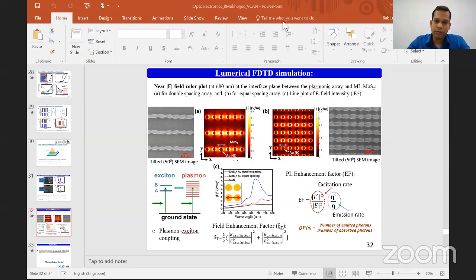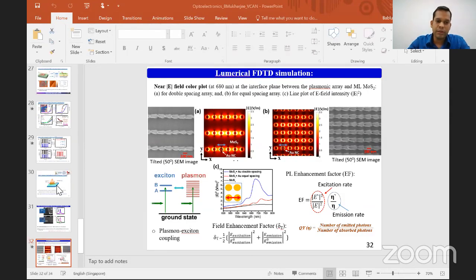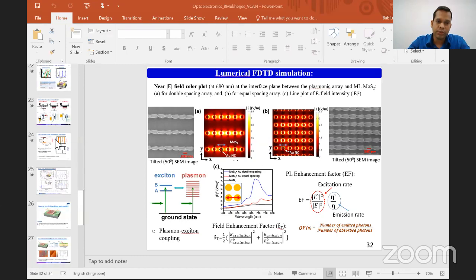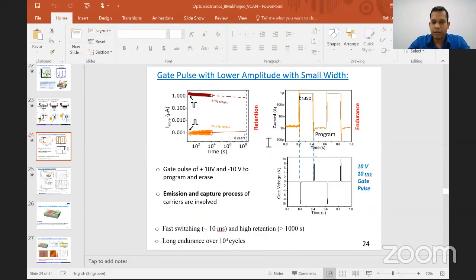Yes, actually, the instrument capability is such that we can do at the highest 10^4. Maybe we can go until 10^5, but we can always extrapolate and have a view of how it will perform. So for the endurance, we believe that it can sustain even higher cycles, but we do not have such experimental data. So we claim until 10^4, which we have.